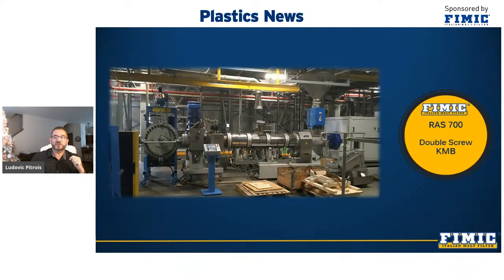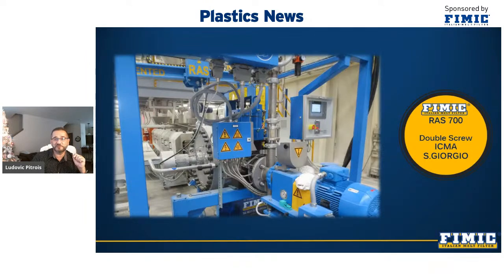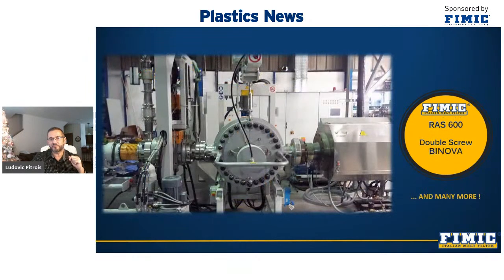KraussMaffei Berstorff twin screws extruder to process washed HDPE at a capacity of 6,160 pounds per hour in a RAS filter with a mesh 700 millimeter in diameter and filtration down to 150 micron. Pretty impressive. ICMA S. Giorgio twin screw for PP with capacity of 4,400 pounds per hour with RAS 700 filter and 200 micron screen. And finally, this is a Binova twin screw extruder for PP with capacity of 3,300 pounds per hour with a RAS 600 filter and 300 micron screen.